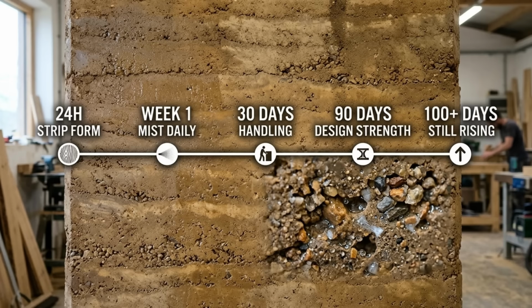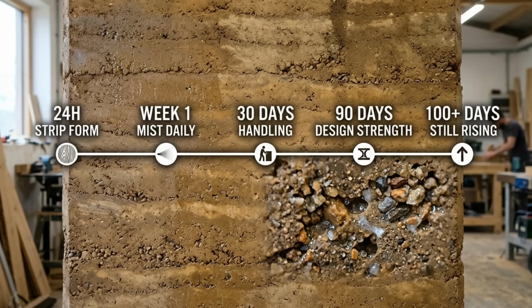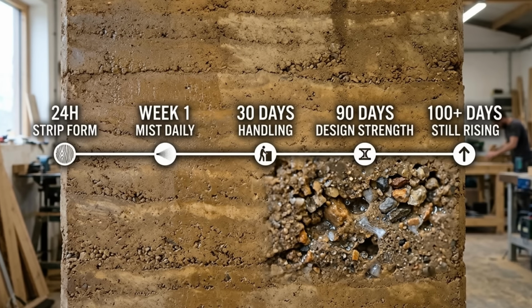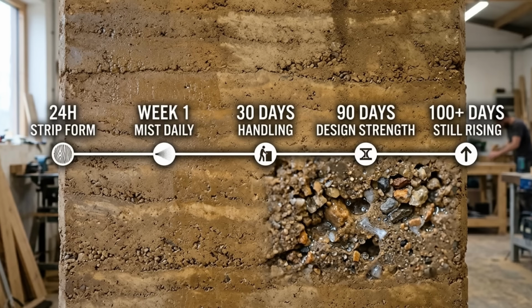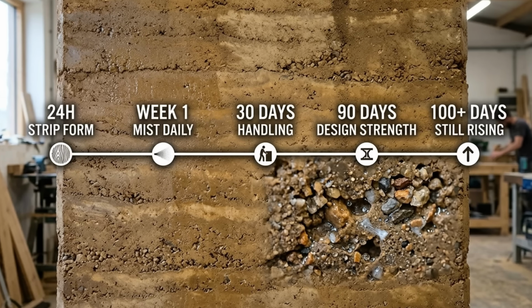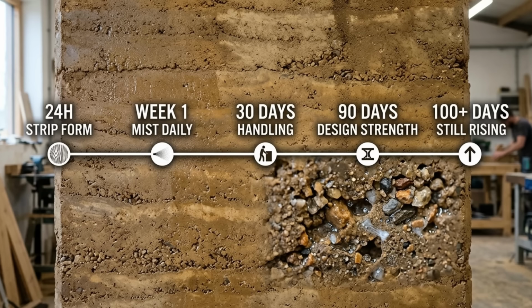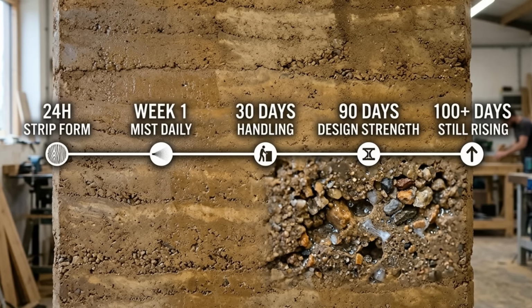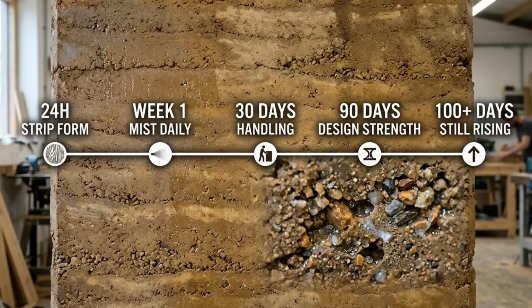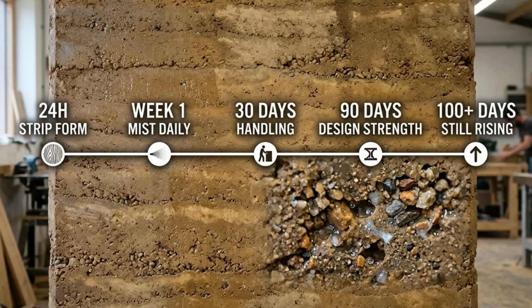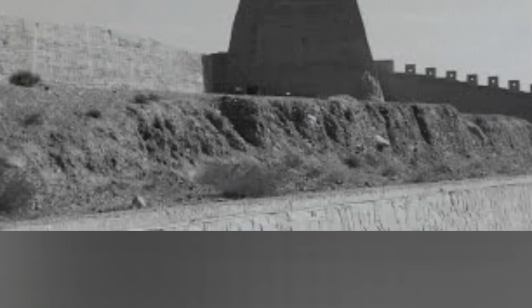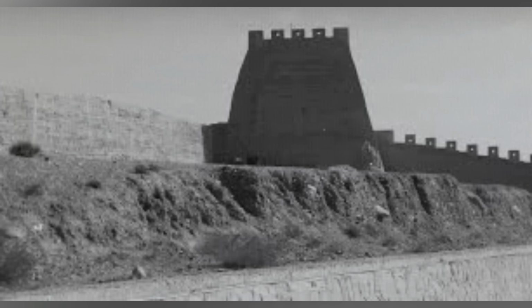Mist the wall lightly with water once a day for the first week. Pozzolanic chemistry needs continuous moisture to keep the calcium silicate hydrate gel forming. Handling strength is reached at about 30 days. Design strength at about 90. Full strength continues to develop for years. The Granada team's data showed strength still increasing measurably past 100 days, with the asymptote not yet reached. Walls built to essentially this protocol in late 19th century rural Leon in northern Spain and across the Loess Plateau are still load-bearing today. No rebar, no chemical sealants, no maintenance schedule.